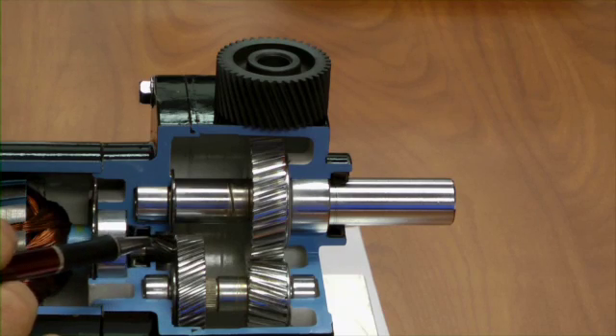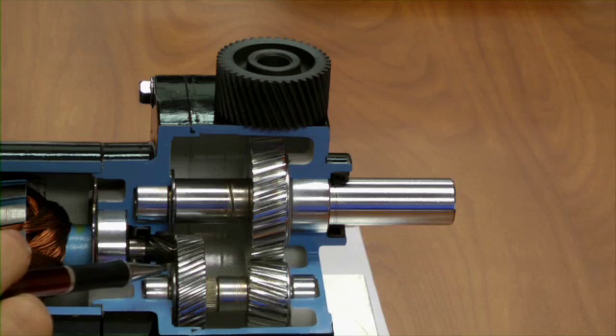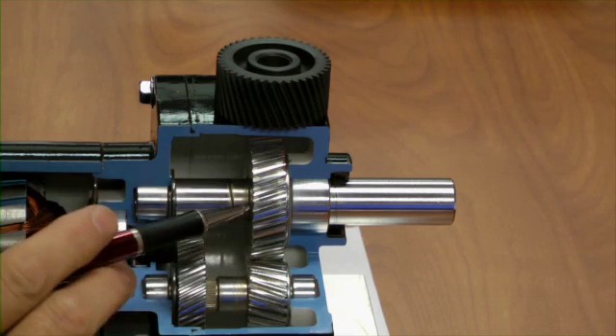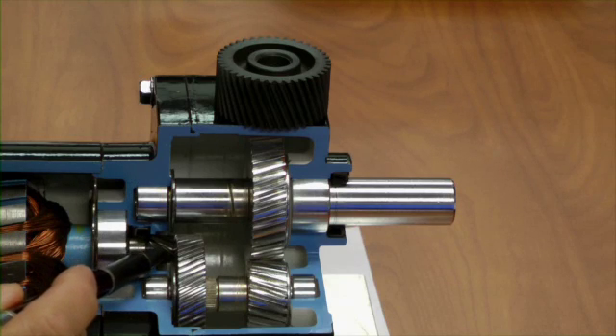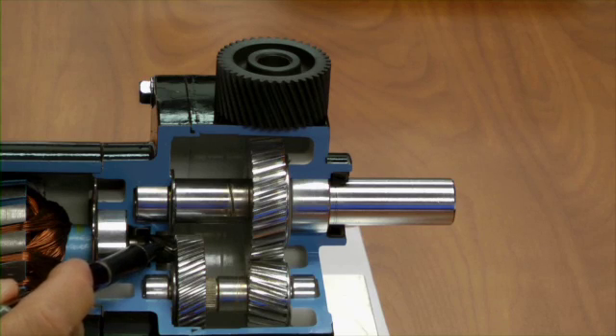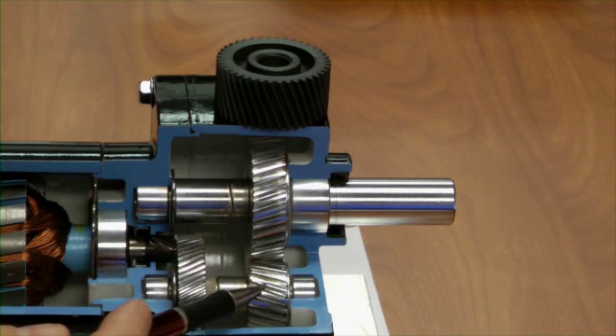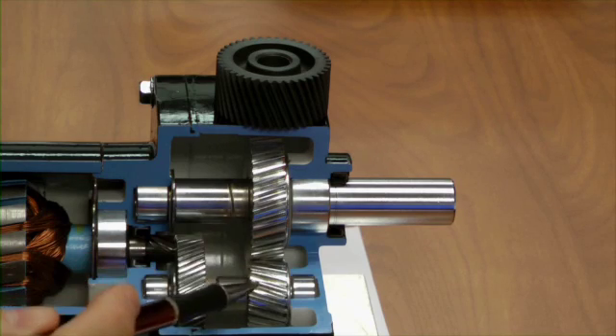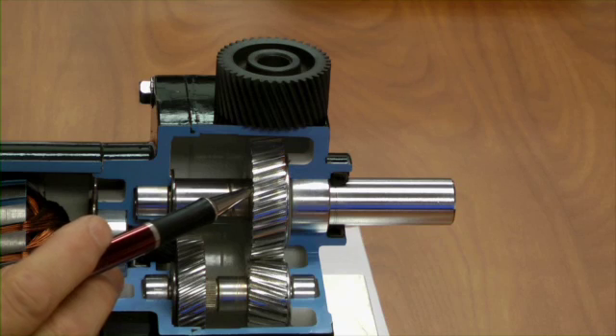In the material selection, which in this case happens to be steel, each one of the stages can be hardened to a different hardness level. So there is always a sacrificial steel, which is usually the larger diameter, which will be a softer steel or a softer hardness. In this case, this pinion, which is hardened to RC-45, this one here is not hardened at all. And by design, it is fatigue proof, which is around RC-30. This one here is hardened to RC-62, because as you can tell, for every rotation of this gear, we probably see three or four of this one. So this one here sees a lot more action, where this hardness here is only RC-58.